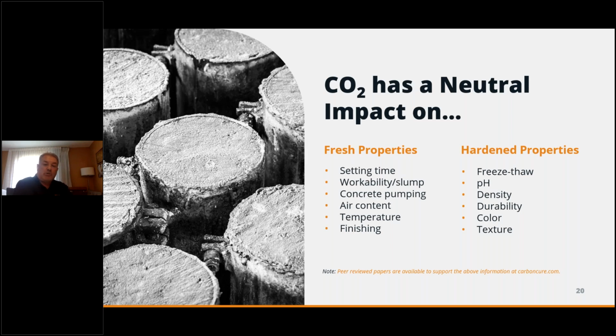They don't want concrete that sets up any longer. They just want what they've always had. And that's really what we try to do, deliver concrete that's just like they had, with a better environmental footprint. From the hardened properties standpoint, we've got some good white papers that support this from a durability perspective, in terms of testing for strength and longer term performance of the concrete in Canada. Things like freeze thaw are particularly important to us, pH levels and what have you. So typically we're not going to impact things differently than you see in the traditional mix designs that you're already using.